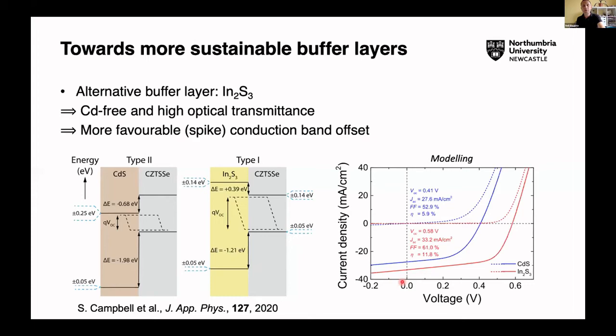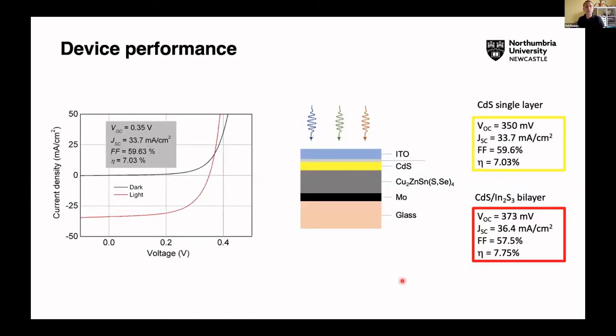And so we set about trying to recreate this experimentally, and here's our conventional system. So there's a device which is around 7% efficient with light and dark IVs. There's its structure, and here's the cadmium sulfide. And then the parameters are in the yellow box on the right.